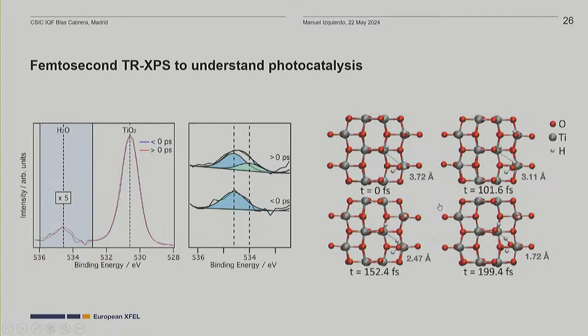You see here snapshots at different times. So here you have 0 femtoseconds, then after 100 femtoseconds, you see that the bond length due to this extra bond is changing, and then this is the final configuration of the system.